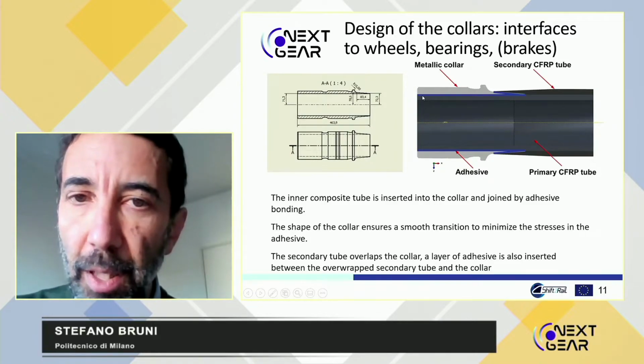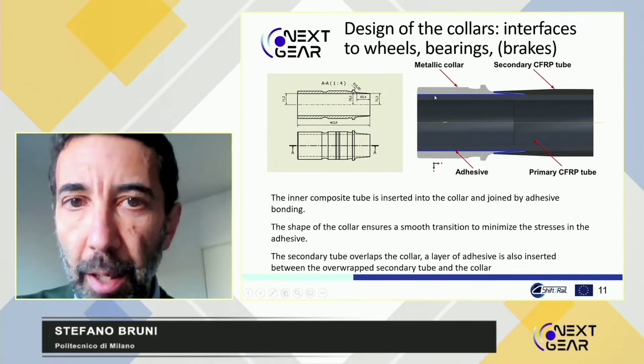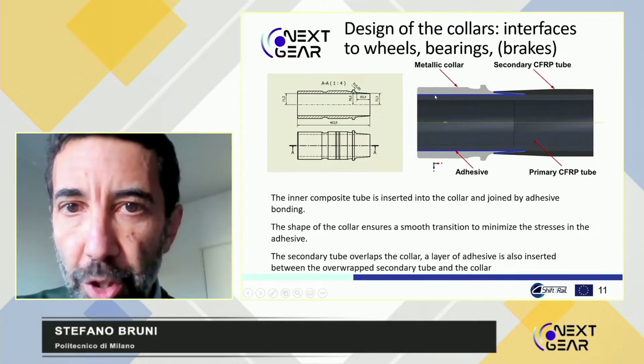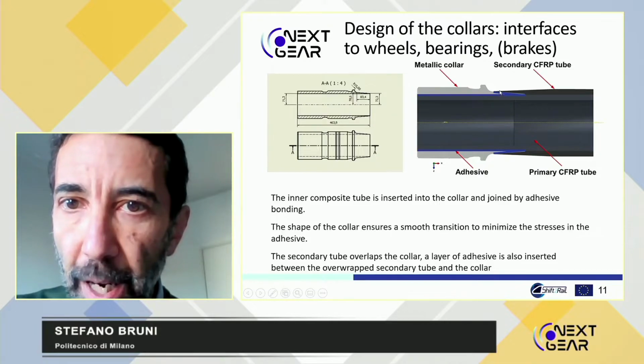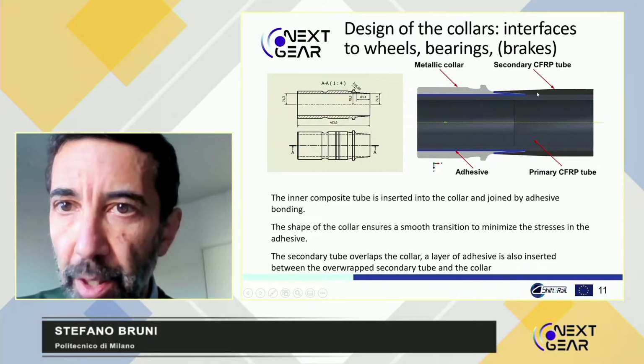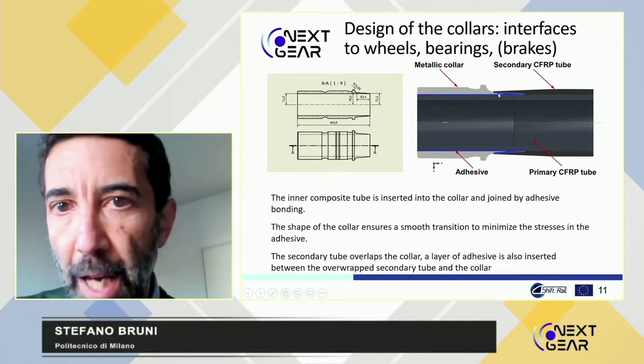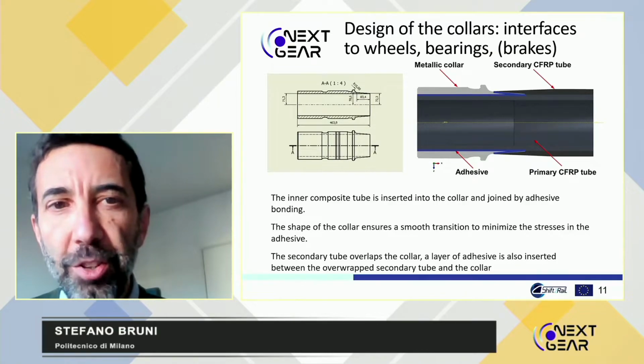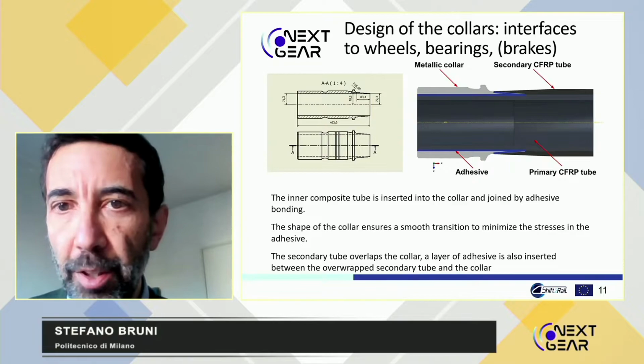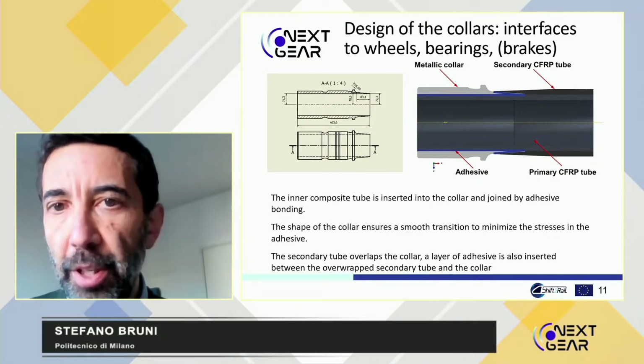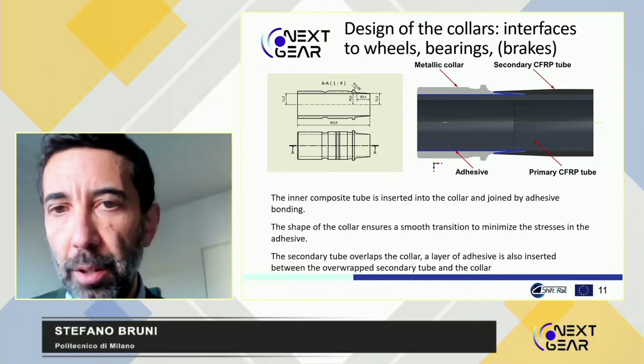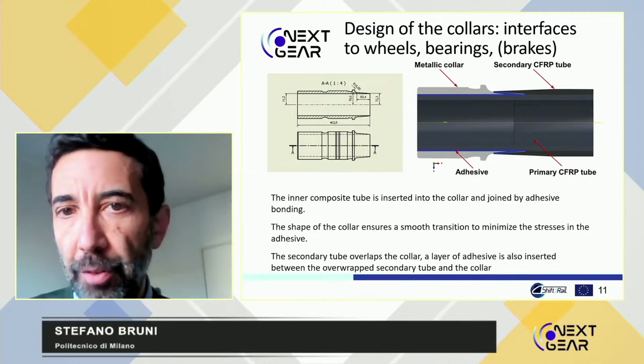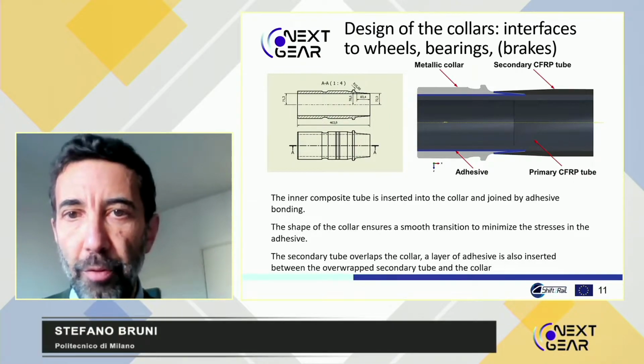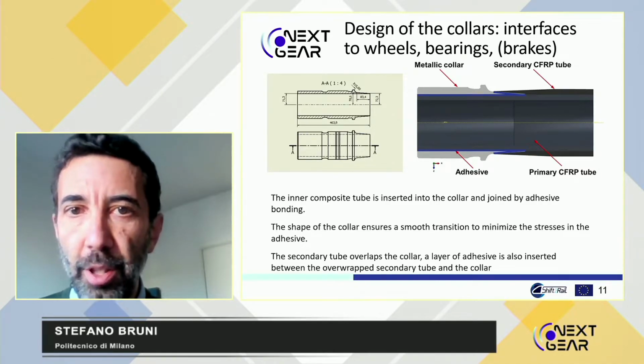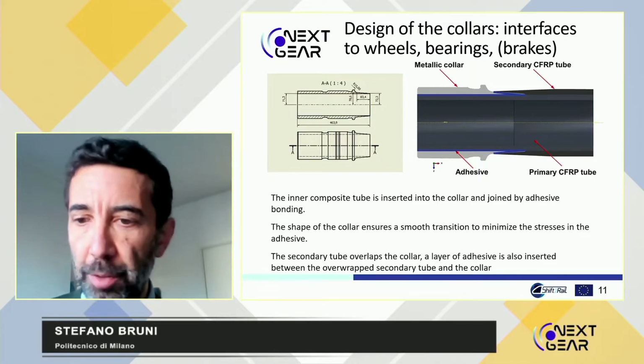You will see that here the adhesive bonding layer is represented by a blue line, which connects, let's say, the metallic collar to the inner tube and then folds back, providing also a connection between the secondary composite tube and the outer part of the metallic collar. So with this solution, we ended up finding a very nice stress distribution in the adhesive material and a solution that would, at least from the point of view of detailed finite element analysis, provide a very safe and durable connection of the metal part to the composite parts of the axle.